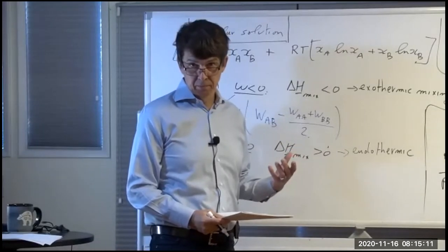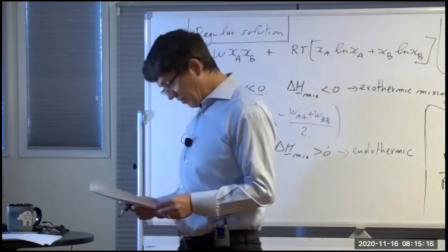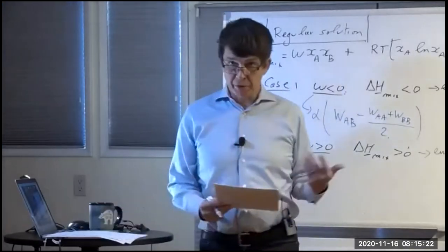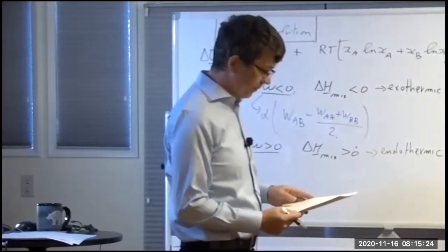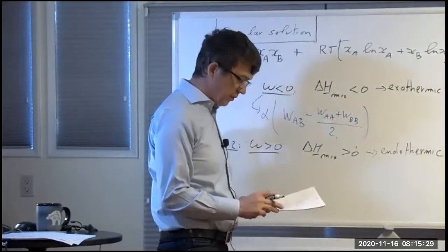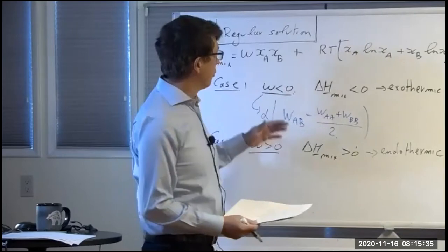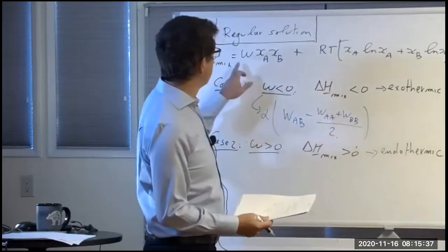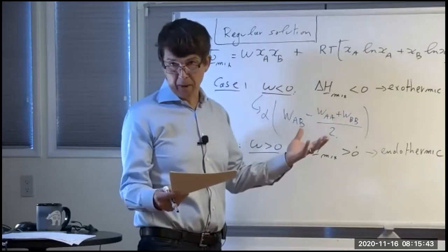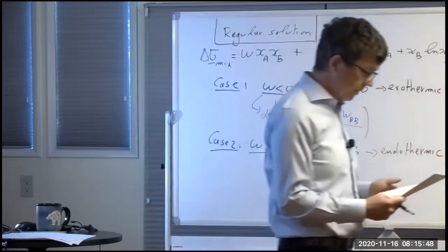Okay, so what's the farthest away from infinity? I guess that's 0, depending on your math world. And so at 0 Kelvin, or as you approach low temperature, you should be careful with this model, and I'll show you a few cases of that. And of course, what does low temperature mean, right? When we talk about low temperature, it means low on the scale of the energetics. If you have a very large energetic parameter, then of course low temperature can actually be high temperature. So it's whatever is low on the scale of omega.